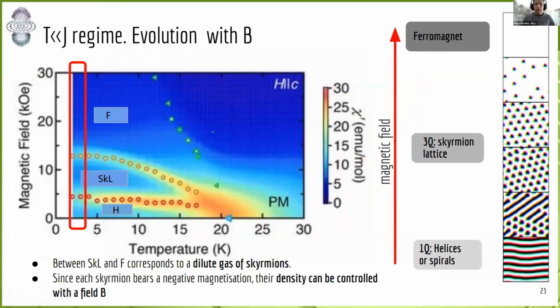Let me show you what happens now at low temperature in this phase diagram, but now as a function of magnetic field. If we start at high field here in the fully polarized regime, the situation is this. All the magnetic moments, now in white, are pointing along the field direction. This is why all of this portion of the lattice is white. But as the magnetic field is decreased, for example at this boundary, you can see the emergence of a small number of skyrmions in black here. This is a kind of gaseous skyrmion. As the magnetic field is decreased again, we arrive at the skyrmion crystal, this one. Finally, at very low field, we arrive at the one-dimensional helical state or spirals.